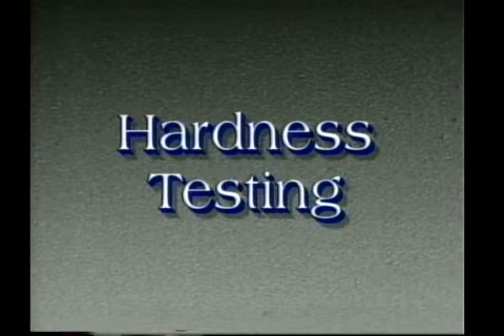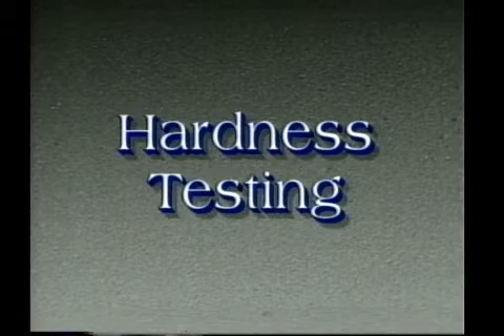Heat-treated aluminum alloys respond to hardness changes in an entirely different manner than do steels. The aluminum hardening reaction is a precipitation reaction, not a martensitic reaction. As a result, the use of hardness measurements, tensile tests, and their relative correlations must be given closer scrutiny and used with extreme care in predicting the usefulness of a heat-treated aluminum alloy part. In most instances, a particular part will function successfully if it possesses adequate strength characteristics. Thus, the tensile test, which provides the material's yield strength, tensile strength, and the level of ductility, as measured by percent elongation, is most useful.